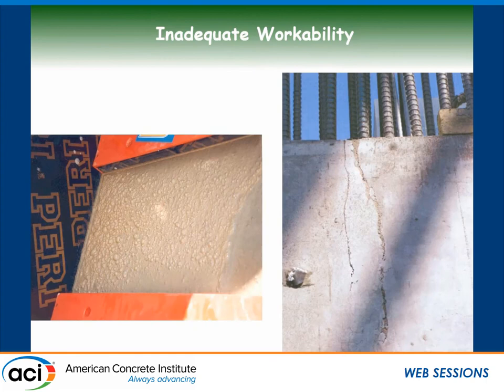And then if you're not paying attention to the concrete, you can get some bleeding. And the previous presenter, I think, alluded exactly to what's happening to the pore pressure, especially in deep structural elements. You can get a buildup of pore pressure, and you have basically water rushing up and giving you some of those bleed channels. So it's not everything that is at the top. There are bleed channels. There's entrapment under rebars and aggregates.